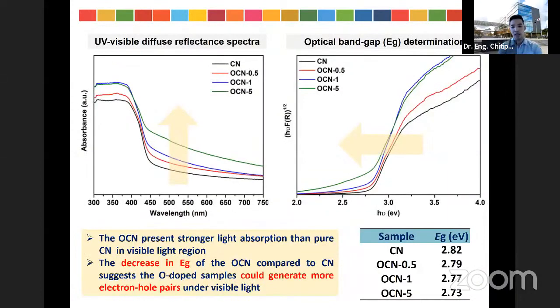And this slide shows the optical property and the energy band gap of all the samples. And it can be seen that the stronger light absorption ability in the visible light region was observed in the oxygen-doped sample than the normal graphite carbon nitride in the background. The OCN sample, or oxygen-doped sample, can harvest more visible light and generate more electrons and holes, resulting in more production of the active species. Also, the oxygen-doped sample, OCN sample, shows the lower energy band gap compared with the CN sample, which is the pristine graphite carbon nitride or undoped sample. So we can expect the decreasing of the energy band gap of the oxygen-doped sample could generate more electron-hole pairs under visible light irradiation.